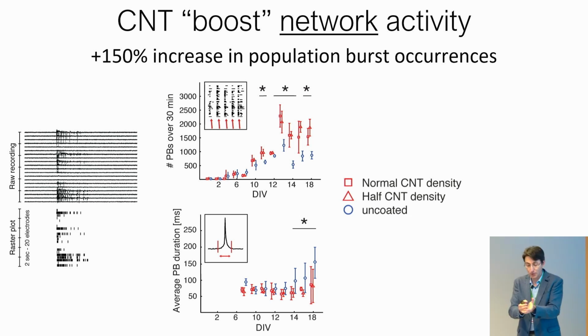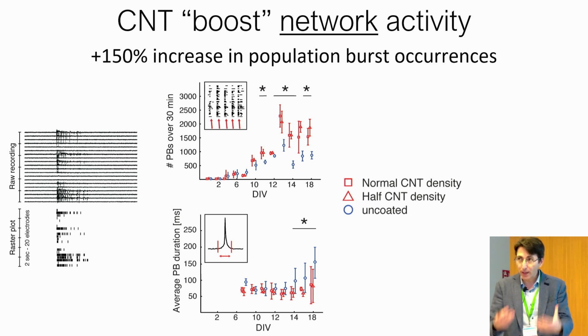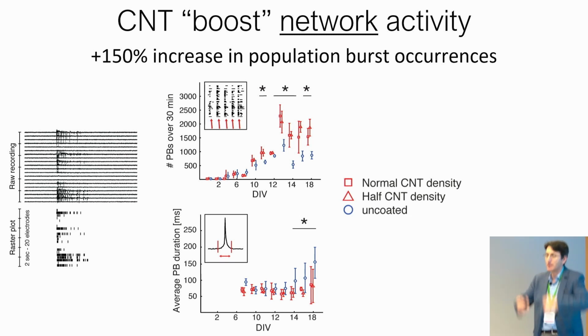What we found, however, is that when you plate neurons on the top of these carbon nanotubes, something interesting happens. So not only you get stronger signals, but the periodic synchronized events that are occurring spontaneously in vitro, and it's probably a proxy of synaptic development. So these neurons are reconnecting into functional networks, and because of this connectivity, they start getting activated over and over. As a function of time in vitro, 2 days, 6 days, up to 18 days after plating, the frequency of these synchronized events that we called burst was increased. It's more than a 150% increase.